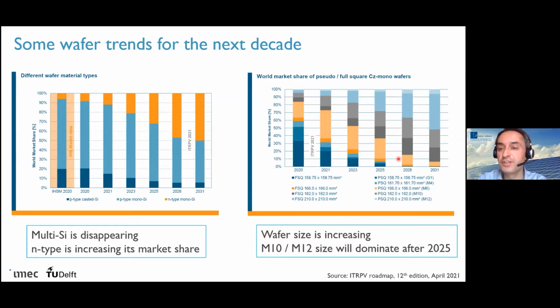It's foreseen that in the future the so-called M10 and M12 sizes will really dominate after 2025. These are still square wafers, with dimensions of 182 by 182 millimeters, or even 210 by 210 millimeters. So we really go to much larger wafers.